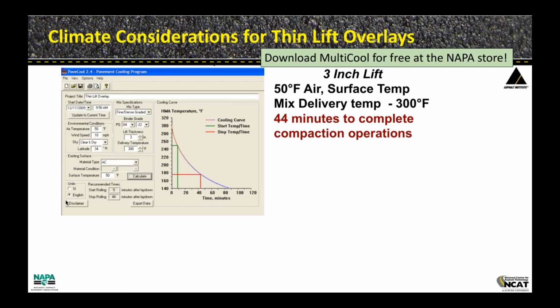For instance, in this example, 50-degree air temperature. We're assuming for this example that the surface temperature was plugged in at 50 degrees. Things like the sky, the latitude, the wind speed, the type of mix, the binder grade, lift thickness. In this case, we put in 3 inches and a mix delivery temperature of 300 degrees Fahrenheit. And then also you can put in preferences as to what you want for a starting and a terminal value for temperature. In other words, in this case, we put in 175 degrees Fahrenheit. So all compaction needs to be done before the mix reaches 175 degrees Fahrenheit.